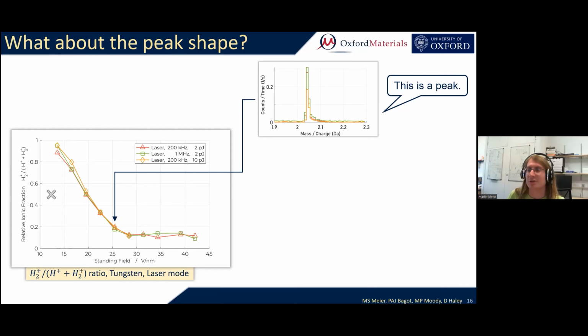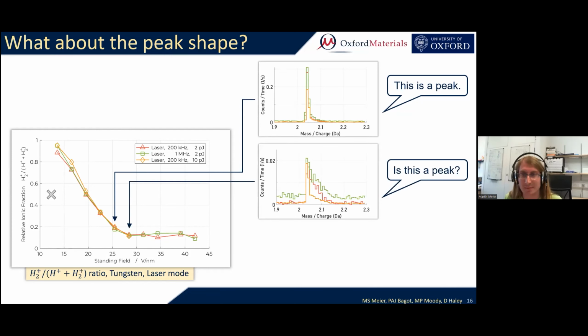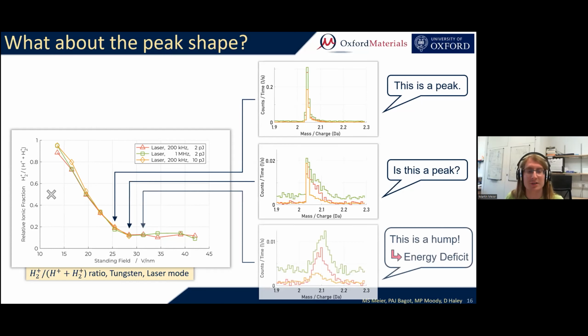But as we go to higher electric fields, this is changing. When we get into this field independent region here, we see that first the peak gets this oddly wide shape, and eventually it is turning into this, and this is what we previously called a hump. This is now an energy deficit that we're observing here, and we find that it is the energy deficit type of hydrogen that is causing all of these odd observations that we make in laser mode at high electric fields.